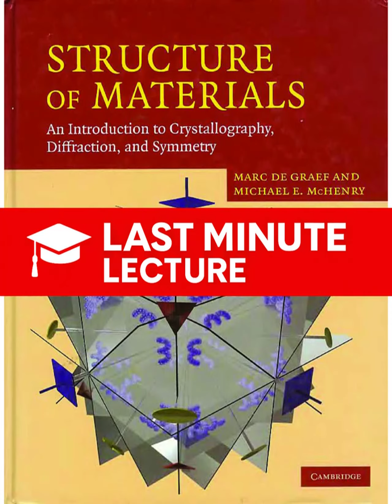Yeah. It's where the incident photon retains its wavelength and its energy. It only experiences a 180-degree phase shift. And crucially, because the wavelength is preserved, all these scattered waves can interfere constructively with waves from neighboring atoms. That's the source of our ordered diffraction pattern. That is the signal, but there's also noise. Right, the scattering event we don't want.